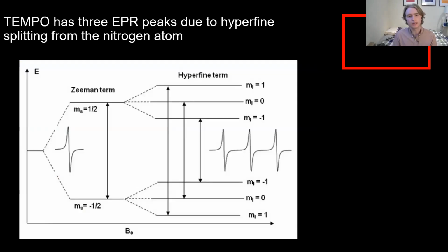So before I really get into talking about my spectra, what you're going to notice is that all of my spectra with TEMPO have 3 EPR peaks. And the reason for this is hyperfine splitting and coupling to the nitrogen atom spin. So we have our electron spin, and now we have the nitrogen atom spin. And remember, I said a lot of the electron density in TEMPO is actually on the nitrogen.